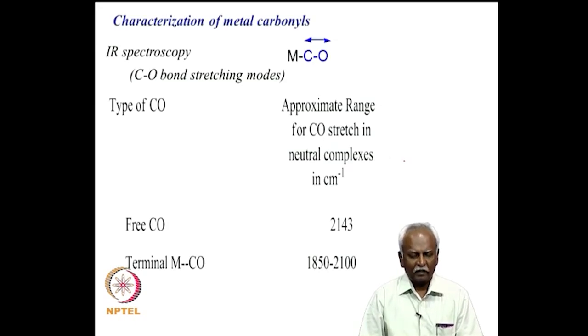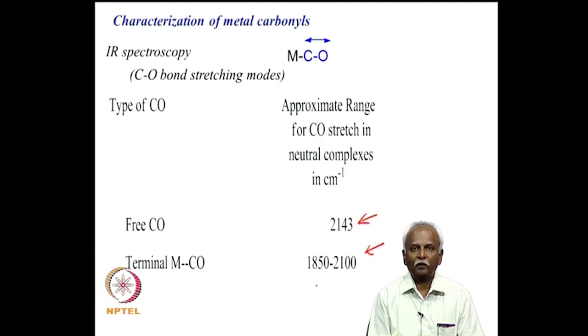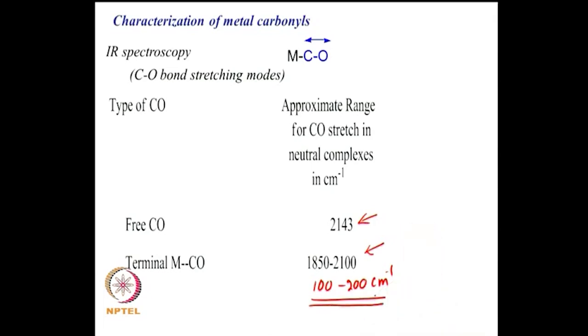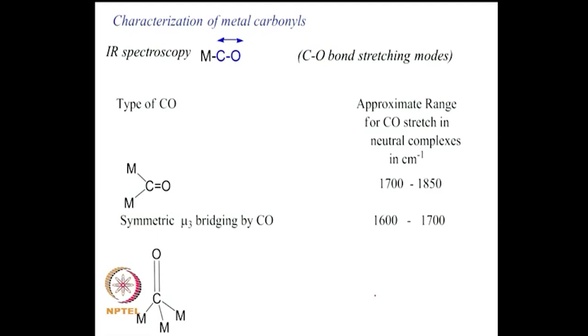Now, let's get back to the fact that the carbon monoxide stretching frequency has reduced from 2143 centimeter minus 1 to 1850 to 2100, approximately 100 to 150 centimeter minus 1 decrease, or 100 to 200 centimeter minus 1 decrease in the stretching frequency. So, this decrease has to be explained when we look at the bonding. So, let's go and look at the bonding that is involved, and we also note the fact that this carbon monoxide stretching can vary depending on the type of carbon monoxide that you have.